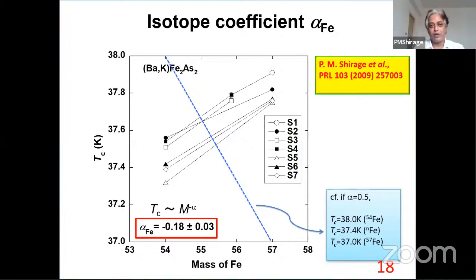But the important and interesting result I got is that with increasing isotopic mass, TC is increasing. This is a very interesting result that we got in this barium iron 2 arsenic 2 superconductor, and it is published in Physical Review Letters. In the 54 iron-based superconductor with this 122 system, TC was around 37.4 Kelvin. When we replaced 54 iron with 57 iron, TC increased to 37.8. So this is a very large inverse isotope effect. This is the first report of the inverse isotope effect. Whatever mechanism was described earlier in history was the positive isotope effect, but this is a negative isotope effect. That's why it's called the inverse isotope effect.